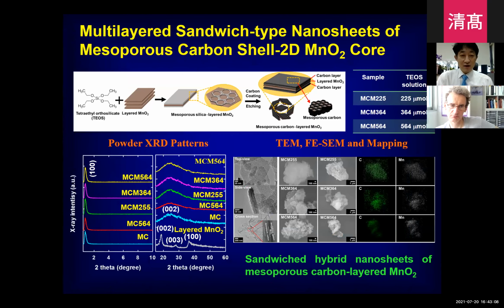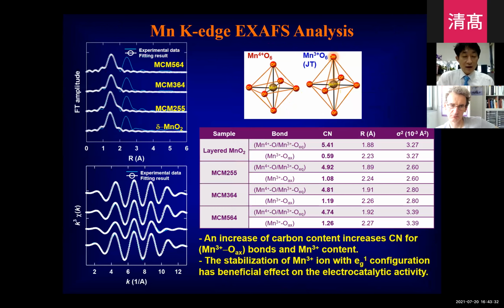This is another type of hybrid nanosheet. In this study, we immobilized the mesoporous carbon layer on the exfoliated layered manganese oxide nanosheet, as you can see here. We can confirm the formation of the sandwich-type hybrid nanostructure from the XRD and TEM analysis. And during such a deposition of mesoporous carbon, we believe that the process induced a change of the chemical bonding nature of local structures.